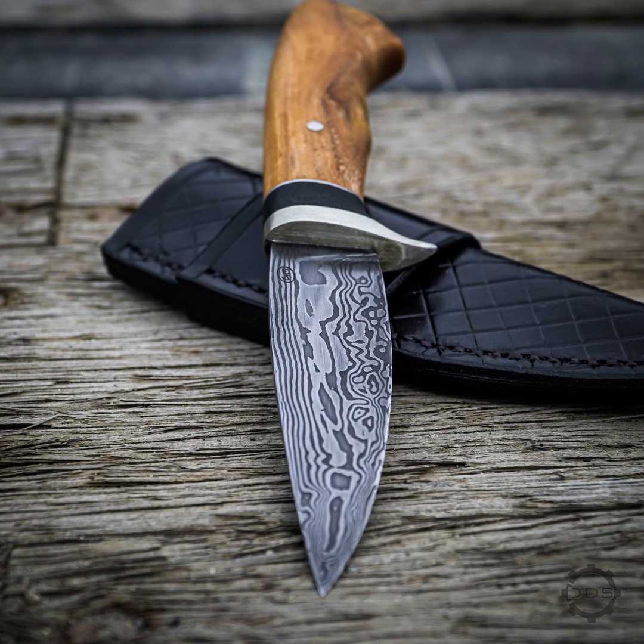And if he says, oh, I forged that blade, but you see that the layers don't compress, like it should be fairly obvious if it looks like they just kind of stop towards the tip, or they just kind of run off and disappear. He did what's called hot cutting, and he cut it to what looks like a tanto when he forged it, and then he forged it in.